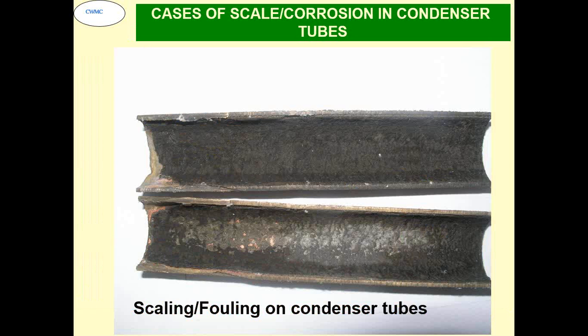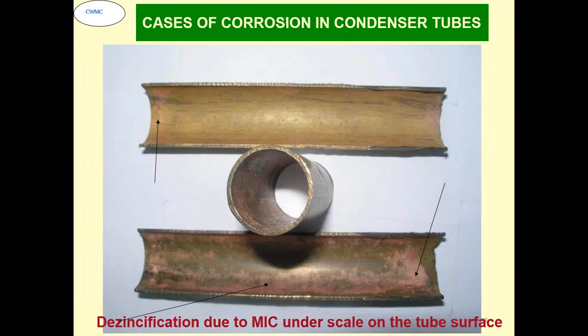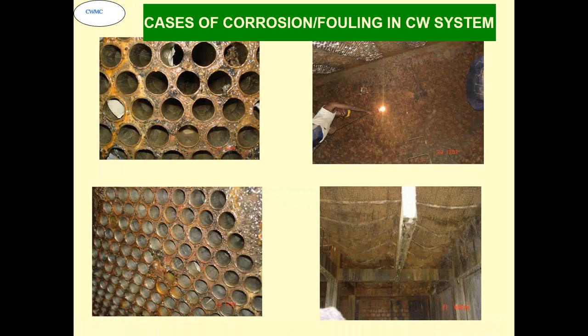Typical organically fouled tubes. This is a dezincification of brass tube because of microbiologically induced corrosion. You can see this portion, the red color what you see. This is all the portion where dezincification has taken place. The zinc has gone out of the solution and the copper has replated on top of that. Typical corrosion and fouling in the CW system.